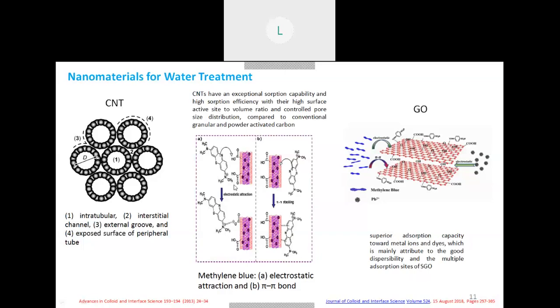Again, after the CNT, the graphene oxides came into the context of the people because of the huge surface area and the higher functionalization. This is the graphene where it is changed with sulfamic acid, and then you will get some other functional groups over it, and that paper is showing the multifunctional activity of the graphene oxides, where you can remove the heavy metals and the methylene blue at the same time.